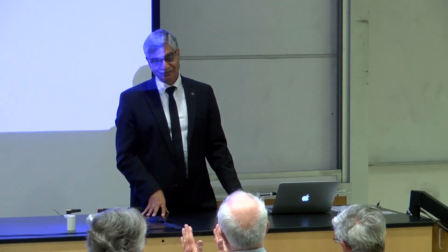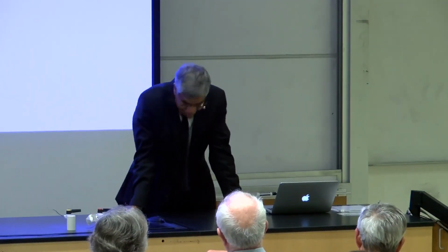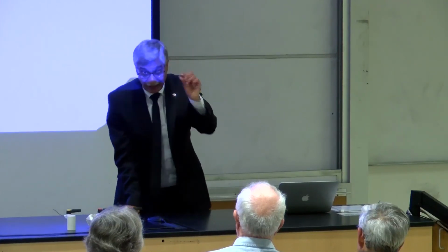Well, let me rephrase something so I think I understand. Even though I'm not using as much of the spectrum, I'm using that portion more efficiently because it's a single layer. Yes, that's right. That's also another part of that. That was the main reason for saying why your yield goes up for photoluminescence. It does not require momentum conservation, which in silicon means the material has to be thick enough, microns or hundreds of microns, because it has to go through the scattering process to pick up that momentum. Otherwise, absorption doesn't take place.